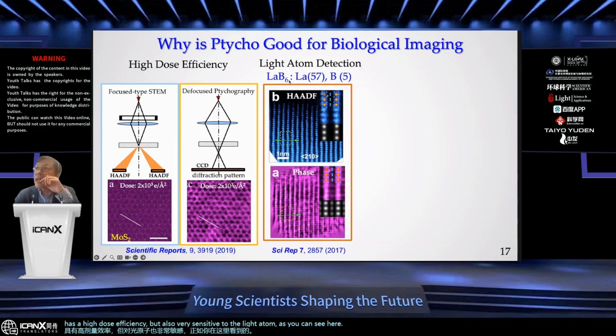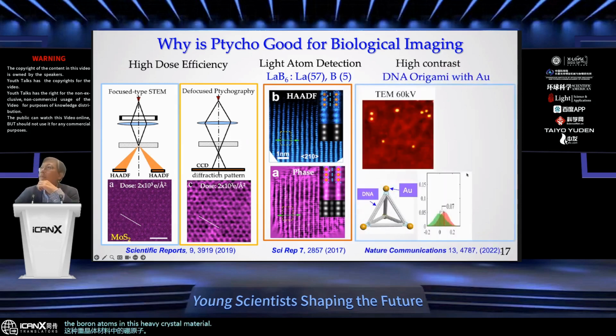Okay, so this is LaB6, and lanthanum has atomic number 57. Boron is 5. In STEM, you won't see any boron atomic columns in the image. However, in ptychography, you start to see the boron atoms in this heavy crystal material. Not only that, but we're also able to see very high contrast of the organic material surrounding this inorganic material.